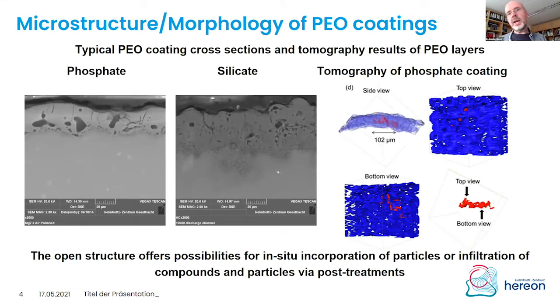When we are looking at the microstructure of those PEO coatings, you see, regardless which electrolyte you're using, whether it is phosphate or silicate, it basically is porous. And we have also studied this porosity in more detail using tomography. It basically turns out that the pore system is very complex. We have lots of pores which are interconnected to other pores. And definitely there are always pores which go from the top of the surface down to the interface. And this is basically critical for the corrosion resistance. But on the other hand, because those pores are already present during the PEO processing, it offers the chance for in situ incorporation of particles or the infiltration of compounds and particles via post-treatments to basically functionalize the PEO surfaces.